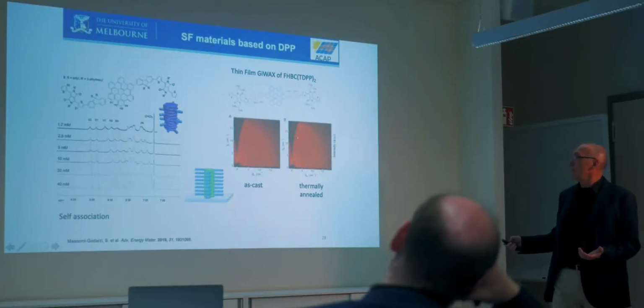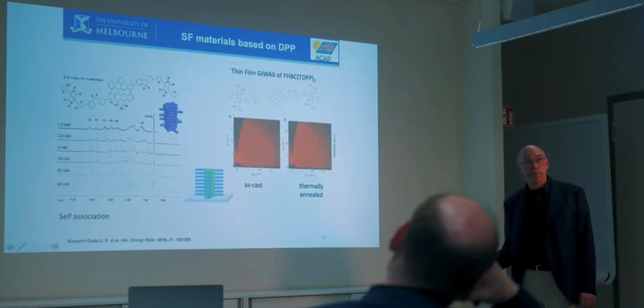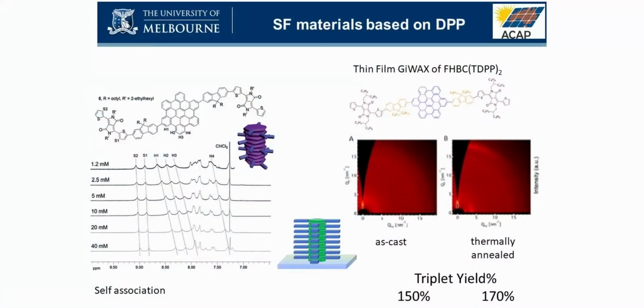However, when we thermally anneal, we start getting peaks here, and there are a few peaks here. Again, sorry, the image is not great. We can index these to hexagonally packed columns. And we can tell by the pi-pi stacking peak here that they come out of the plane. So they have everything we really want. And I'm not going to go into all the really high-level transient absorption spectroscopy, but when we measured these, the triplet yields for the as cast was 150%, and the annealed was 170%. So our first attempt at this gave us really good yields, singlet fission yield, in the solid state for this